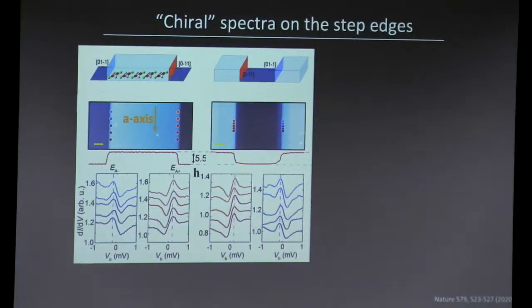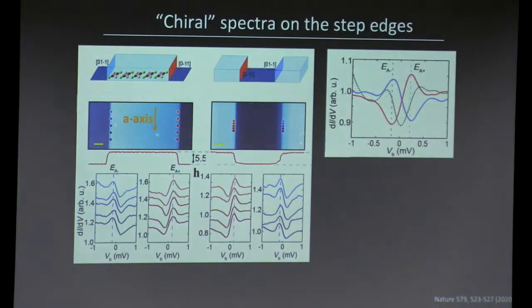So this is the first observation: density of states inside the superconducting gap emerges along the step edge, with this funny character where it appears on only one side of the Fermi energy or the other. We don't actually understand what's going on here.